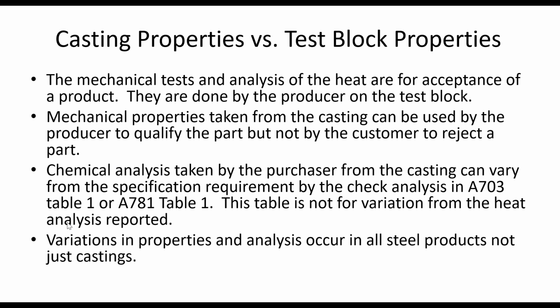In the same way, if you do a chemical analysis, in ASTM, it gives a table, in A703 and A781, that says that the specification becomes wider. So the check analysis is not to see that you get close to the heat analysis I report. The check analysis makes the specification wider so that my casting is still in spec, even if it doesn't meet the specification of the grade, as long as it meets the specification widened by the check analysis in Table 1. So this table is not for the variation from the heat analysis, it's for the variation from the specification itself. And what you should recognize is variation in properties and analysis occur in all steel products, not just castings.